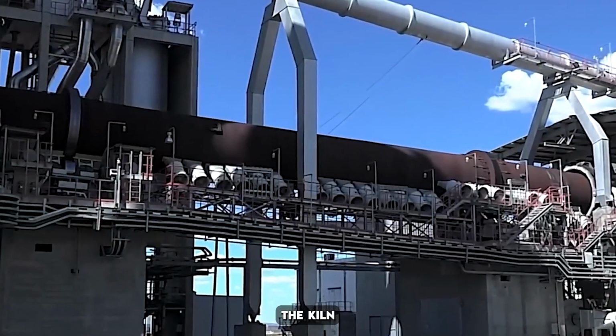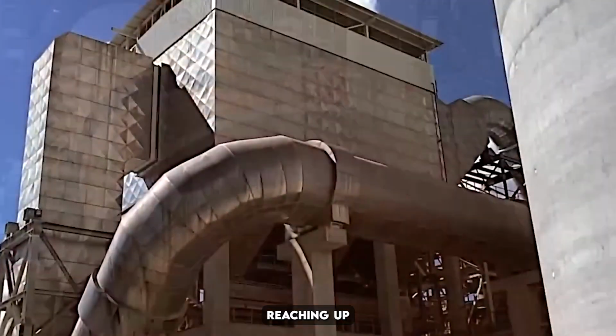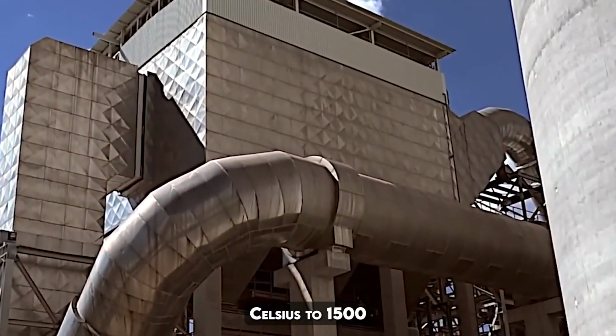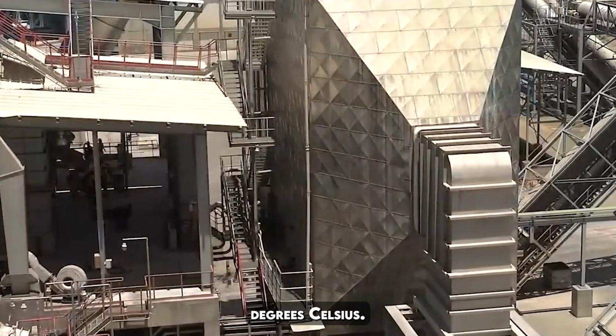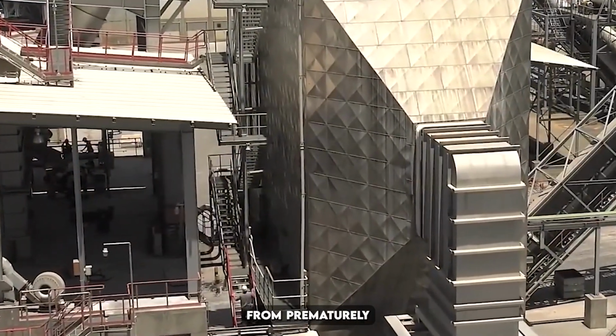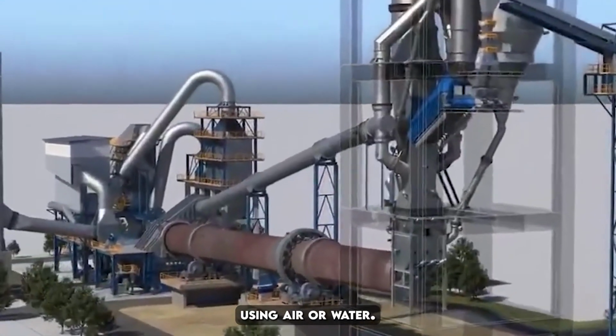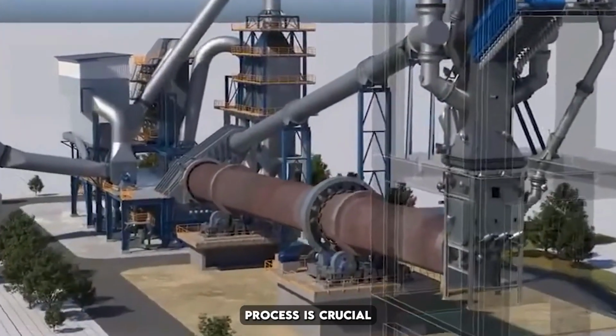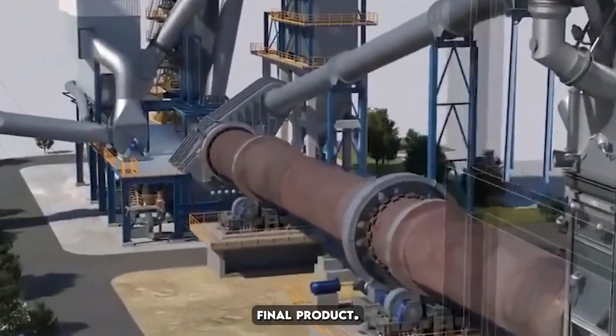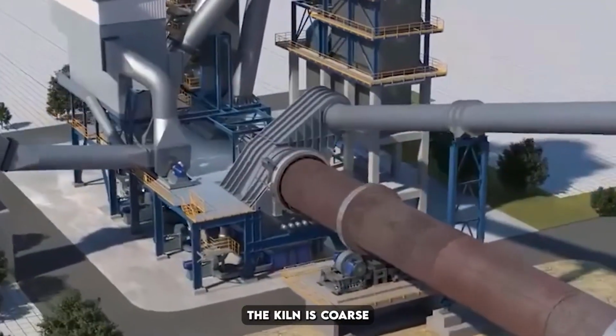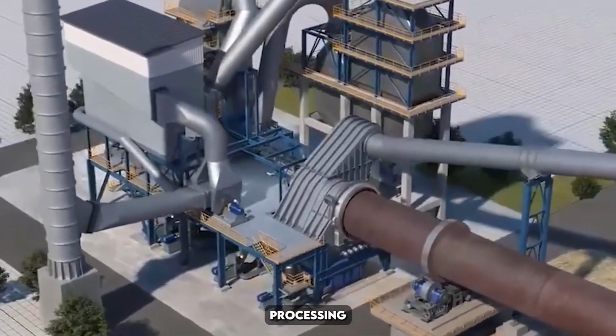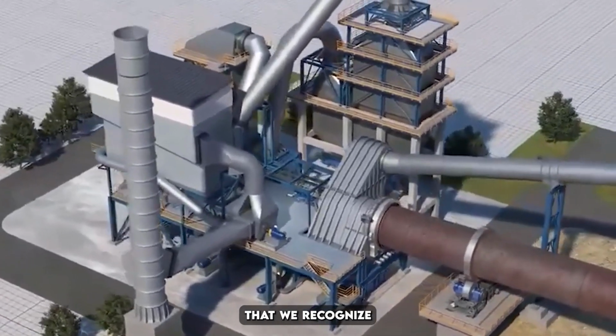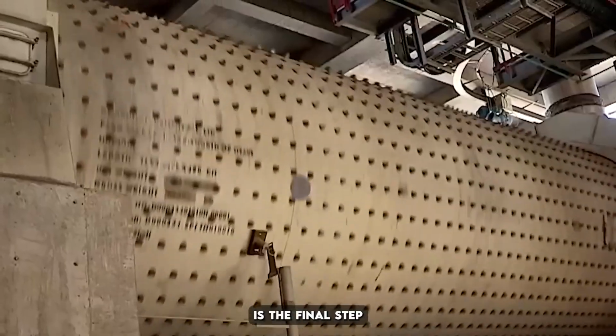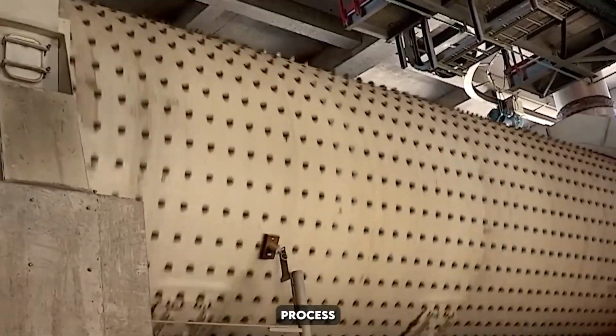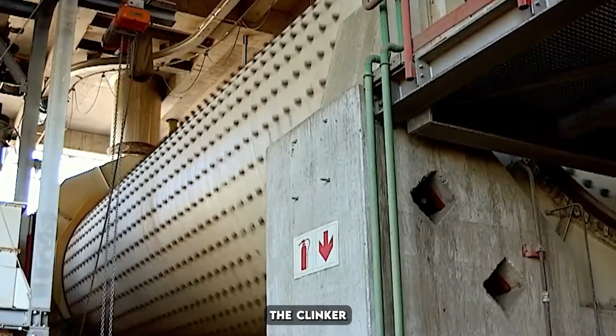The clinker produced in the kiln is extremely hot, with temperatures reaching up to 1,400 degrees Celsius to 1,500 degrees Celsius. To prevent the clinker from prematurely hardening, it is rapidly cooled using air or water. This cooling process is crucial for the quality of the final product. The clinker obtained from the kiln is coarse and needs further processing to become the fine powder that we recognize as cement. Clinker grinding is the final step in the cement manufacturing process and involves finely grinding the clinker along with a small amount of gypsum to control setting.